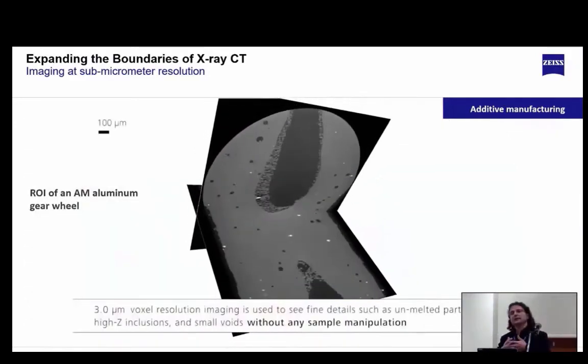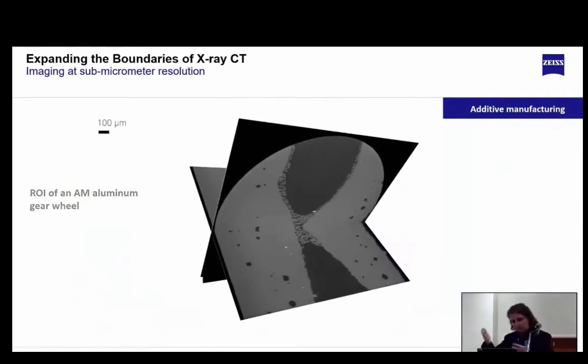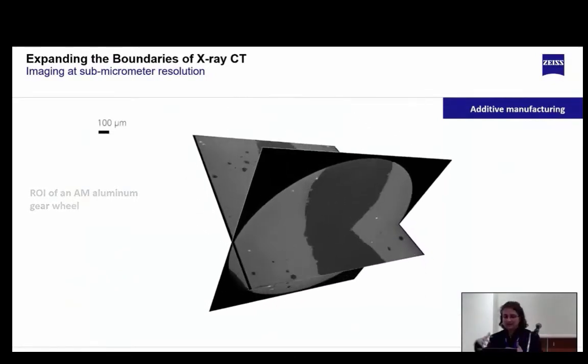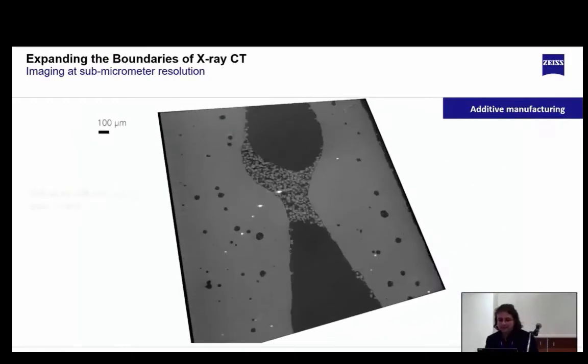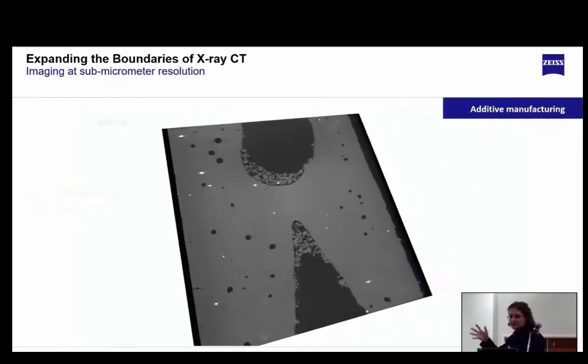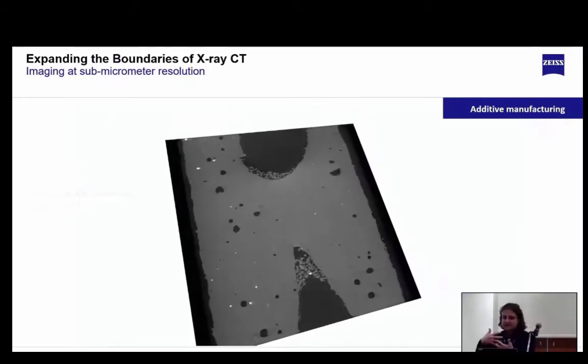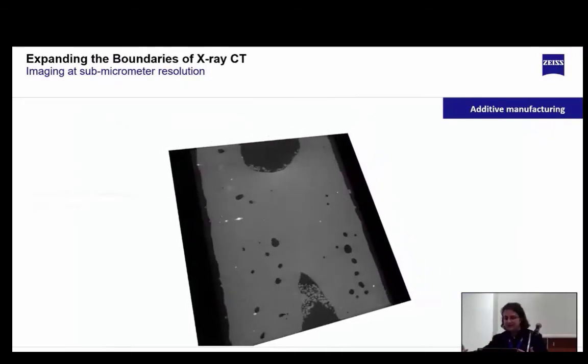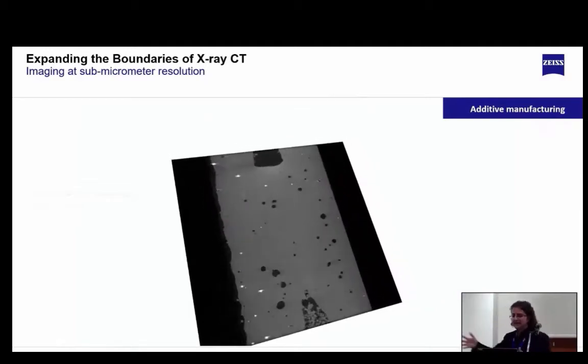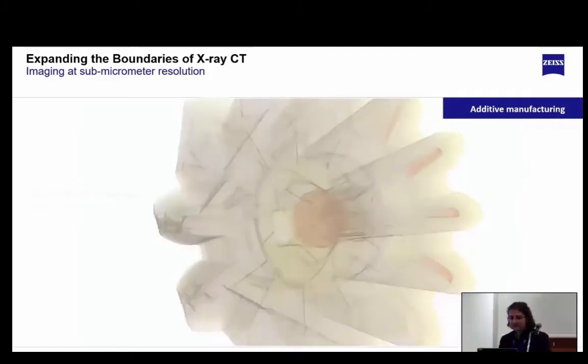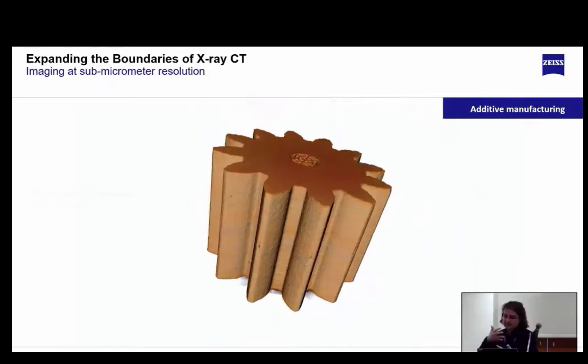This small portion of an aluminum gear wheel, also made by additive manufacturing, illustrates a little bit of this application. This has been scanned with a 3 micrometer voxel size resolution, which allows the inspection of porosity, unmelted powder particles in the finished part, and the detection of unexpected particle inclusions in the powder. All sorts of defects that might affect the functional performance of the part can be detected without destroying the part, with X-ray computed tomography at high resolution if we use the so-called 3D X-ray microscopes.